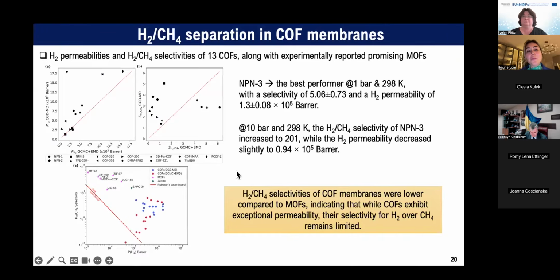Finally, in membrane design, you can compute permeability and selectivity, and this is the general figure that you can see in membrane papers. X-axis is permeability, y-axis is selectivity. I will focus on the C part, so you can follow me more easily. The red line shows Robeson's upper bound. This upper bound is established for polymeric membranes to represent the trade-off between permeability and selectivity. What we found here is that COFs are highly permeable, but they are not selective enough to compete with the MOF structures that we have in our hands.